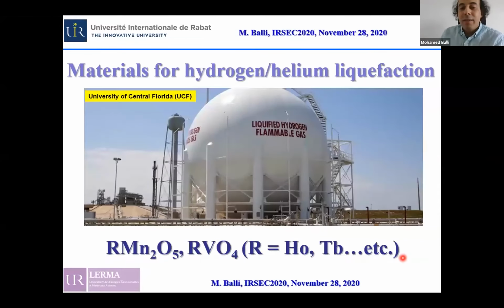And in this way, this family of oxides, which are rare earth manganate and rare earth vanadate, could be serious alternatives to garnet due to their outstanding magnetocaloric properties in the temperature range under 50 Kelvin. So in the following, I will try to present some interesting results in relation with the magnetism and the magnetocaloric effect in some selected compounds belonging to both families. And I will start with the rare earth manganate multiferroics.